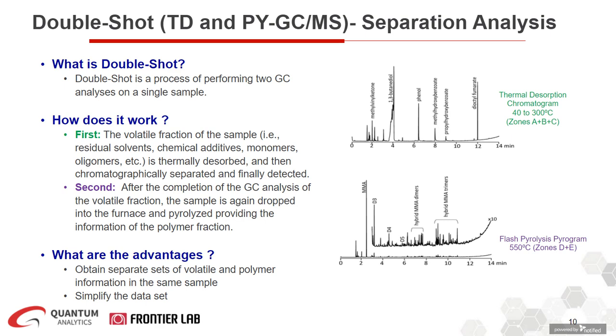Third mode of operation, a double shot. So what is a double shot analysis? Double shot is a process of performing two GC analyses on one sample. How does it work? First, the volatile fraction of the sample, such as any residual solvents that you might have, chemical additives, monomers, oligomers, are all thermally desorbed, and then chromatographically separated and identified by MS.